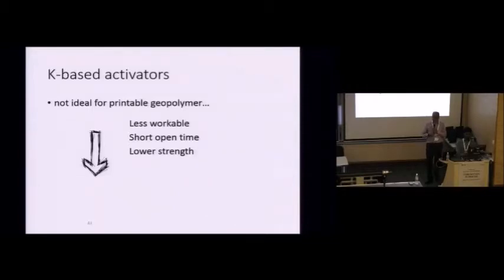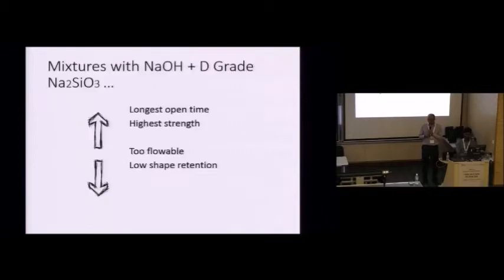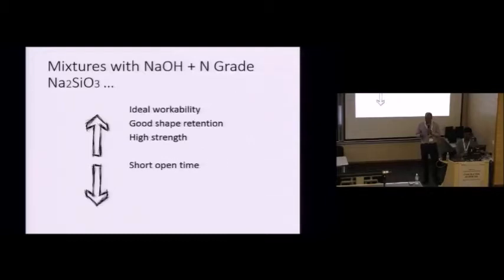Different activators showing different times. So what we found was the potassium-based activators, they're not that workable. They don't have very good open time. And they're also very low on strength. Sodium hydroxide with D grade. There's two grades of sodium silicate that's commonly available. The D grade is good in some aspects, but the best one is the N grade. It gives all the good properties, but it has short open times. That means you've got to mix the activator towards the end of the mixing cycle.